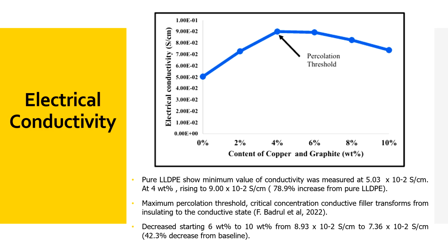In terms of electrical conductivity, we can see the influence of various hybrid copper loading had increased the electrical conductivity of the polymer composite due to incorporation of conductive filler, in this case the copper and graphite. The increase in electrical conductivity is because our material has reached the percolation threshold, which is the critical concentration of filler contact that can transform the material from an insulating to a conductive state.